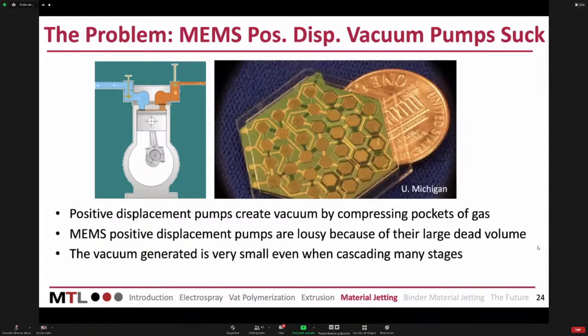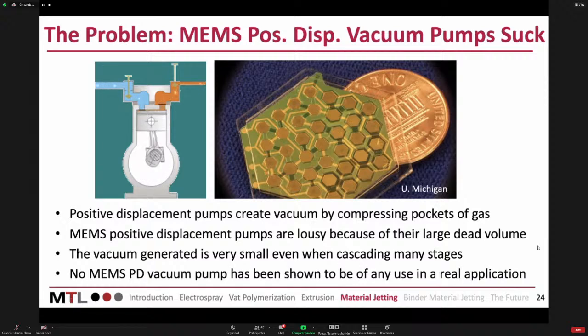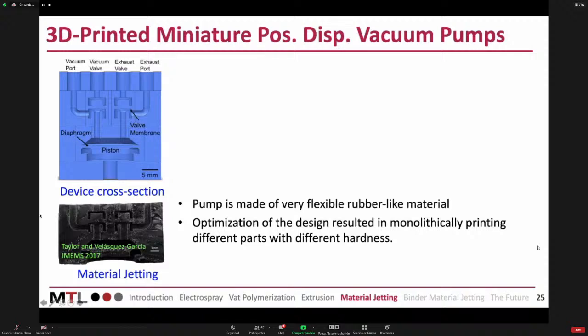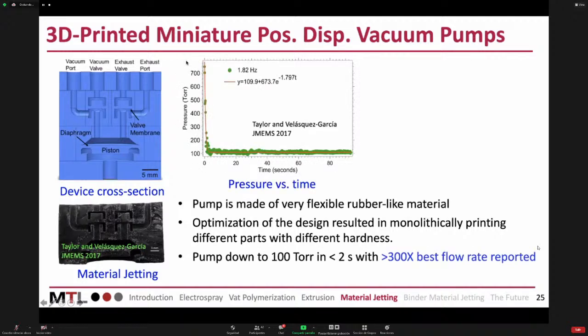So people have come up with very intricate designs. That's a design from Michigan that has many of these actuators, and they cannot get any decent vacuum. So the reality is that these devices don't really do it and have never been used in a practical application. So what we did is come out with a structure that I described at the very beginning, where you have a piston and you have these membranes that you cycle, and with that, you can create very good vacuum. So you can go from 800 torr to 100 torr within a few seconds and maintain it, right?